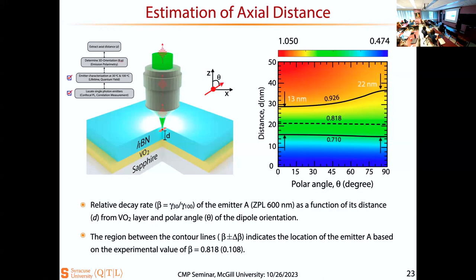So let's say you don't know the polar orientation, you don't know the angle. Then we know the color center is located at about 24 or 25 nanometers, and the full width of the uncertainty is from 13 nanometers to 22 nanometers. So this is already pretty good. I really know it is about 20 nanometers, and the uncertainty is anything from 13 to 22. But we wanted to go a little farther than that.